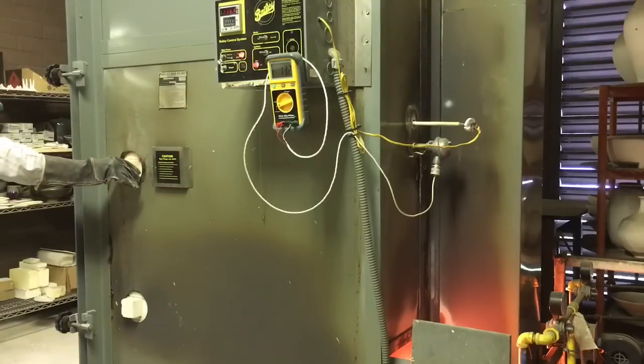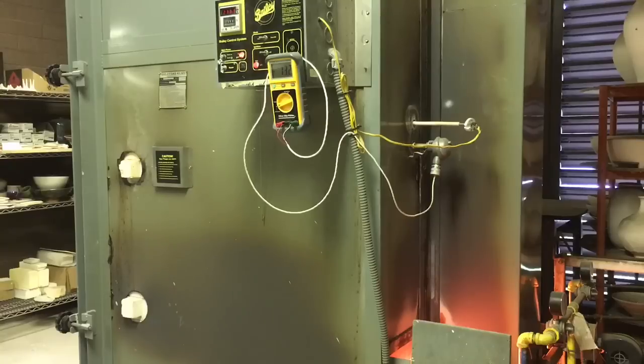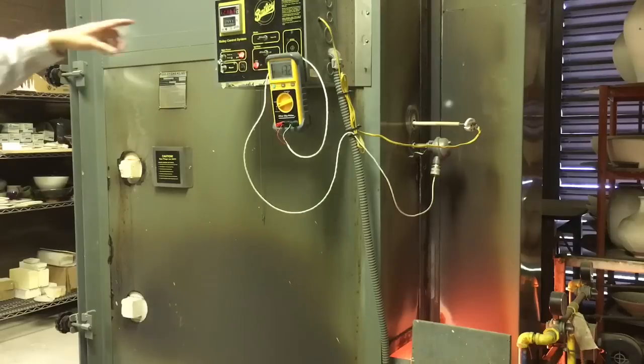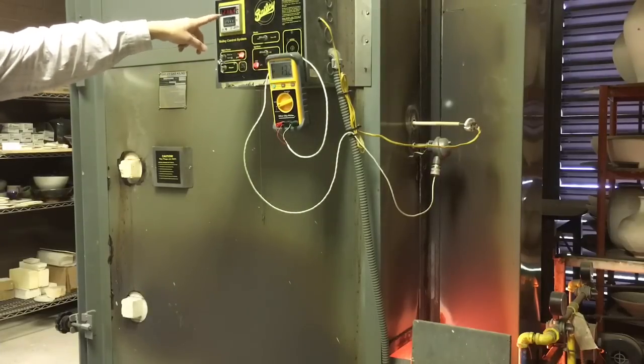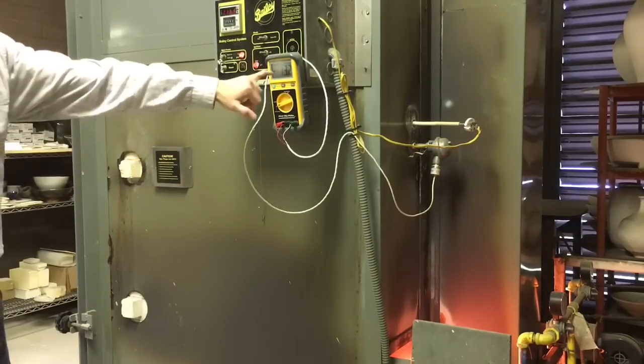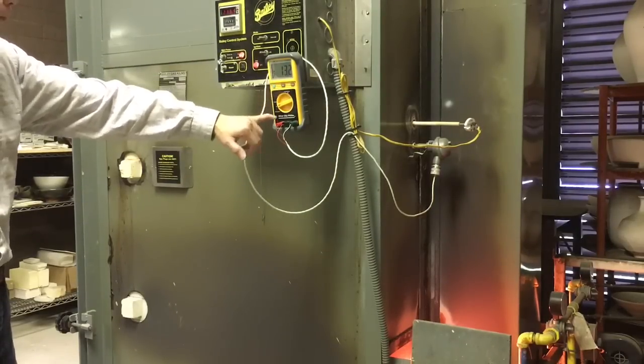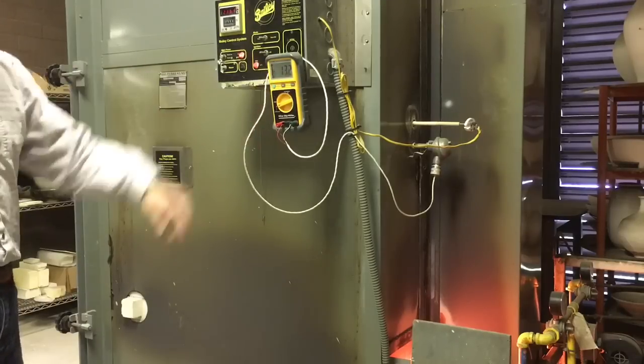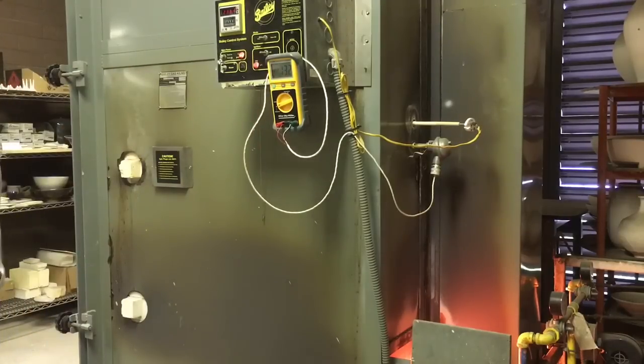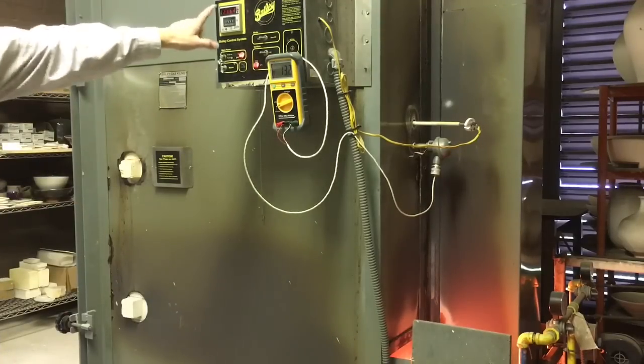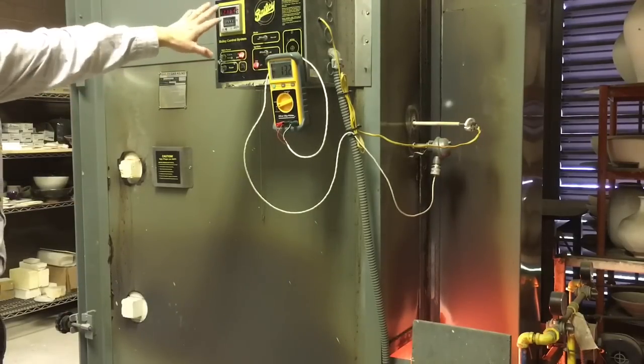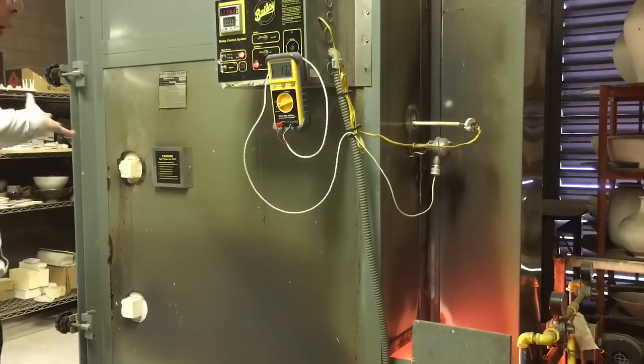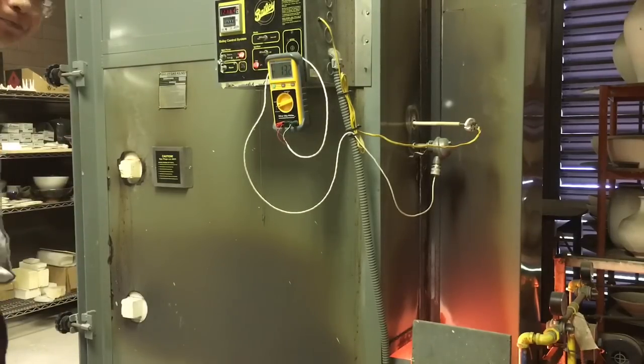So I'm ready to shut the kiln off. The temperature now is reading at 2333. For the meter here, the oxygen probe is reading 13.2. But we shut the kiln according to the cone, not according to the reading of the meter here. So cone 11 is done, so I'm ready to shut it off.